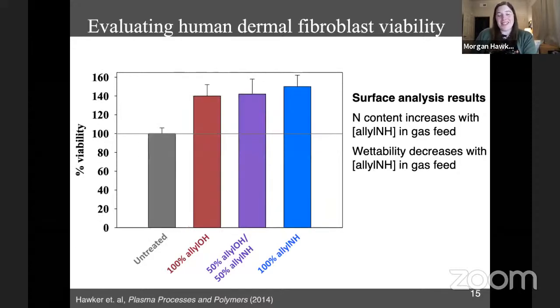Now, what we actually saw, of course, was neither of these predicted results, as usual. We actually saw that all treatments enhanced cell viability when compared to the untreated control, which suggested that both nitrogen content and wettability can be used as tools to promote cell viability.